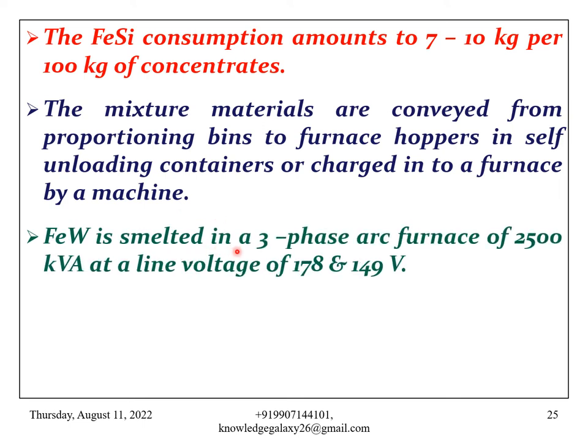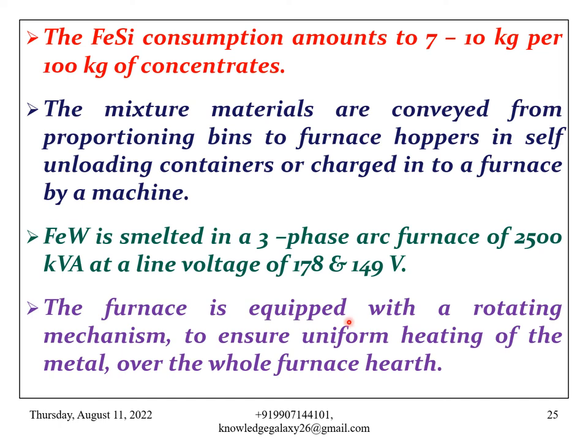Ferrotungsten is smelted in a three-phase arc furnace of 2500 kVA at a line voltage of 178 and 149 volt. The furnace is equipped with a rotating mechanism to ensure uniform heating of the metal over the whole furnace hearth. My dear friends, this is a very important technical aspect of the ferrotungsten smelting furnace. So always do keep it in mind.